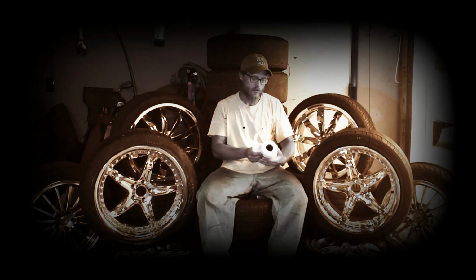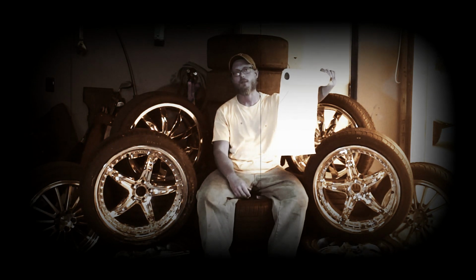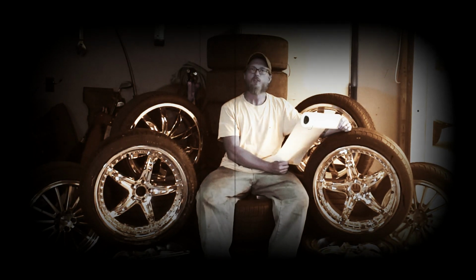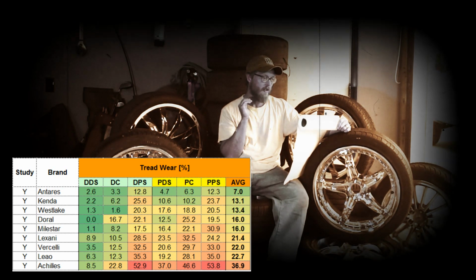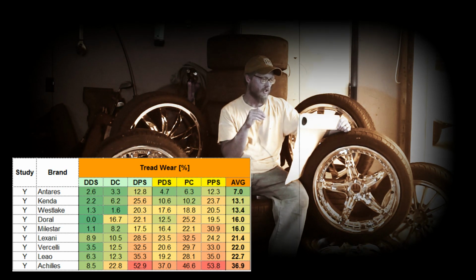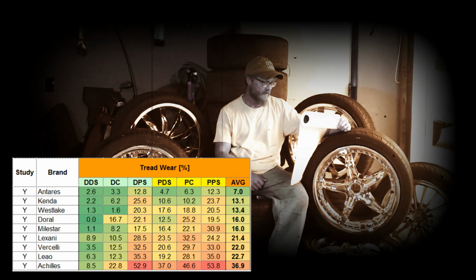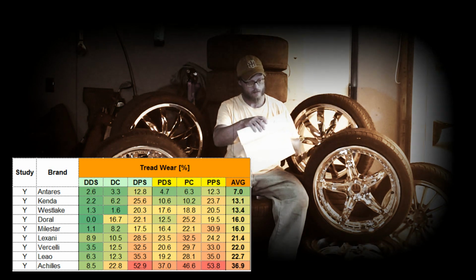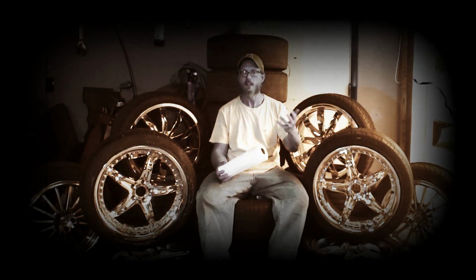So if I consult my ancient scroll of wisdom, I can see here that based on the last video, which I'm going to put a link in the description and you should watch if you're interested in this kind of stuff, just based on initial wear after the heat cycle, the Antares were in front with 7% induced wear, followed by everyone's favorite, the Kenda, followed by Westlake, followed by Doral. Midfield we have the Milestar, then there's the Lexani, which are big boys here, sparkly ones. The Leaos came in second to last, and finally the completely obliterated Achilles. So the Achilles basically got shredded to the point where 1/3 of them was gone after just a heat cycle.